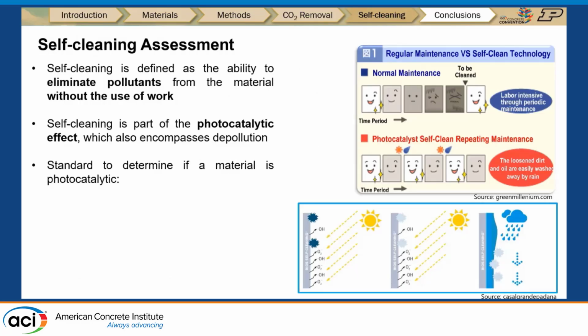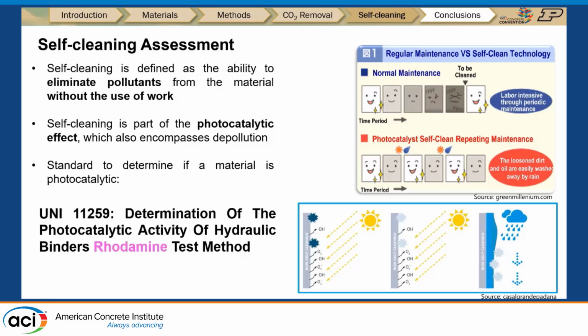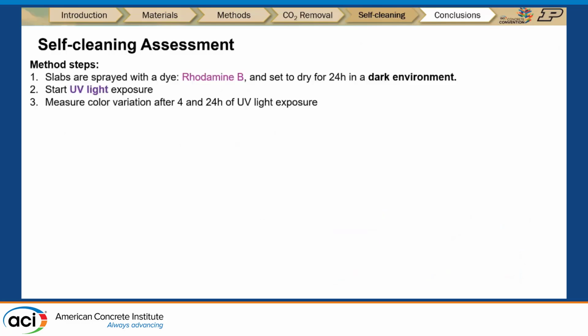Another test we did is the self-cleaning assessment. The self-cleaning assessment means that we want this ability to eliminate the pollutant without the use of work. It's one of the photocatalytic properties we have, and in order to do that, we follow an Italian standard, UNI 11259. The standard specifies that the slabs need to be sprayed with a pink dye, an organic dye called rhodamine B, and set to dry for 24 hours in a dark environment.